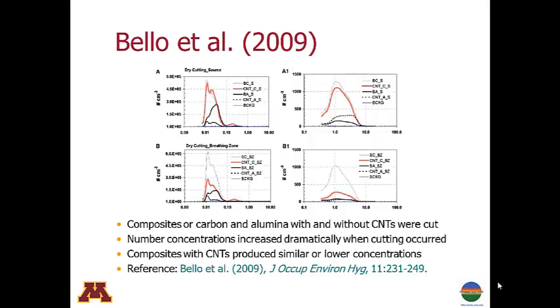Other authors have produced results similar to ours. For example, in 2009, Bello and co-authors were able to observe the cutting of carbon and alumina composite materials created with and without carbon nanotubes as reinforcing agents. The most relevant figures to look at here are the ones on the left that show particle size distributions at the nanoscale. When the materials were cut, the figures show that the composites containing carbon nanotubes generated the same or lower concentrations of nanoscale particles than those without the nanotubes.